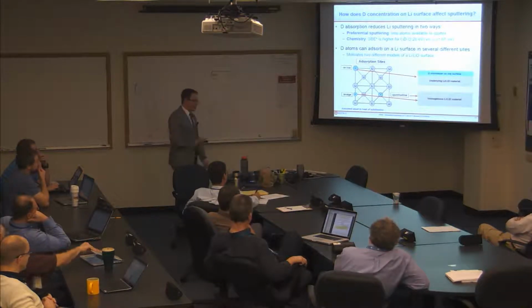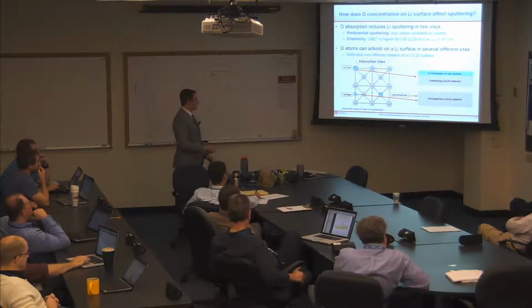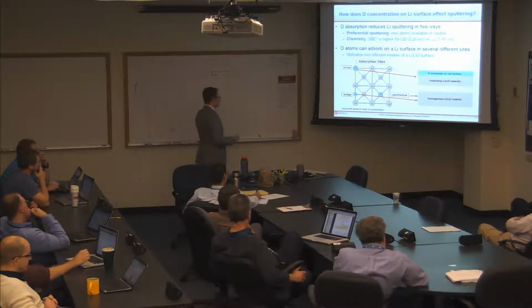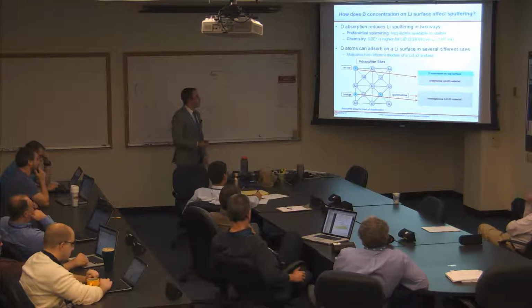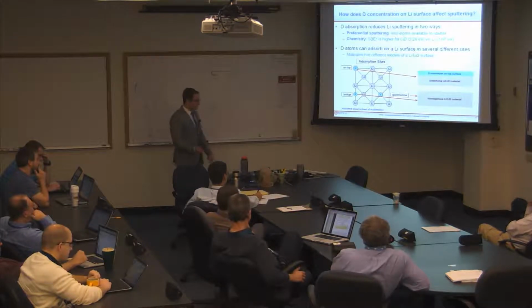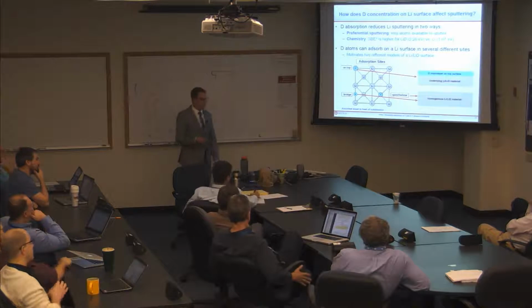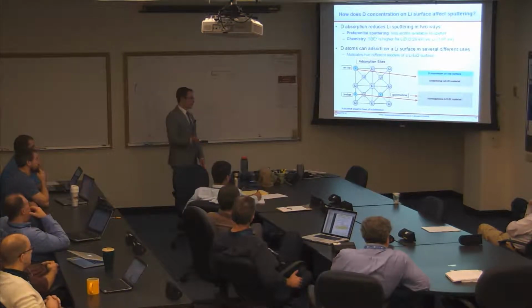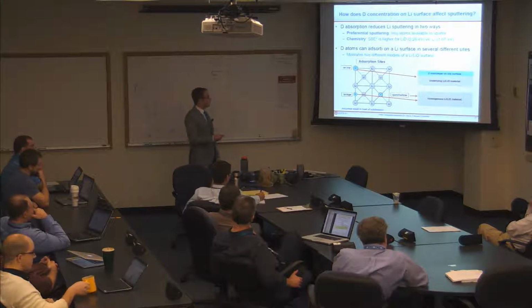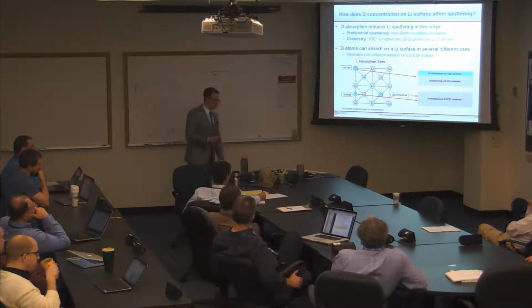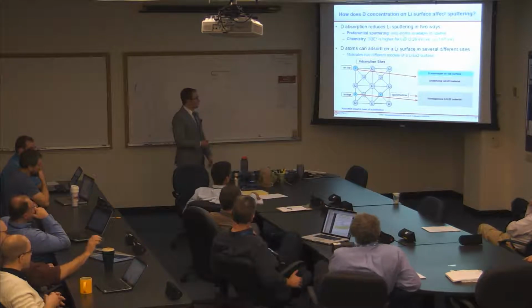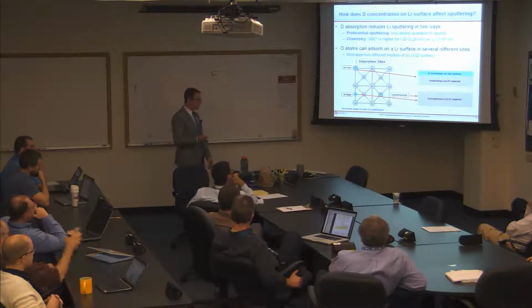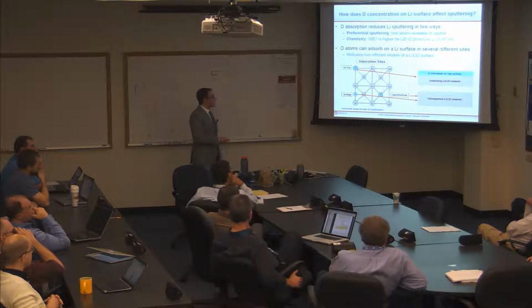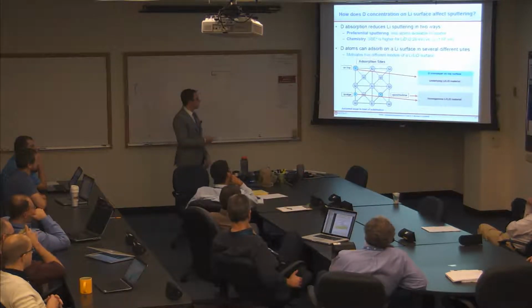Okay, so now we have some approximation for the concentration as a function of time and fluence and flux and temperature. And so we want to know, how does this actually affect the lithium erosion rate? Well, the adsorption and implantation of deuterium into a lithium surface is expected to reduce lithium sputtering in two ways. The first one is called preferential sputtering, which I mentioned earlier, which is essentially a dilution of lithium atoms on your surface, and the deuterium is also sputtered more efficiently than the lithium. And then you also have chemical effects, which I also alluded to before.